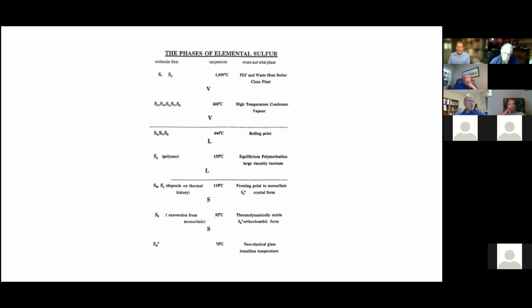Sulfur is an element which has several allotropic forms which are stable, which is your S2, S4, S6, S7. Now these molecules break up, and you have free radicals at either end that join up. This happens at the high temperatures, above about 160 degrees or so. And then you start forming long chain polymers. This is why your viscosity goes up, because these polymers are formed. And also this is important, as you start cooling, it's completely reversible. As you drop the temperature, it reverses back to the cyclooctasulfur form.